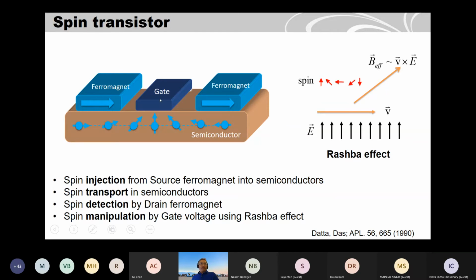And by applying a gate voltage, what you would like to do is change the orientation of spin. This principle of applying gate to change the spin orientation is called the Rashba effect. Because Rashba initially proposed, long ago, that when your electrons are moving with velocity v and you have a material with high spin orbit coupling, and where the inversion symmetry is broken, then when you apply an electric field, this will give rise to a net magnetic field in the material. So the effective magnetic field the electron experiences will be the cross product of the electric field you apply and the velocity of electrons. So with this effective magnetic field, spins will start to precess. So you should be able to manipulate the spin of the electron by the gate voltage. So this electric field from the gate will change the orientation.